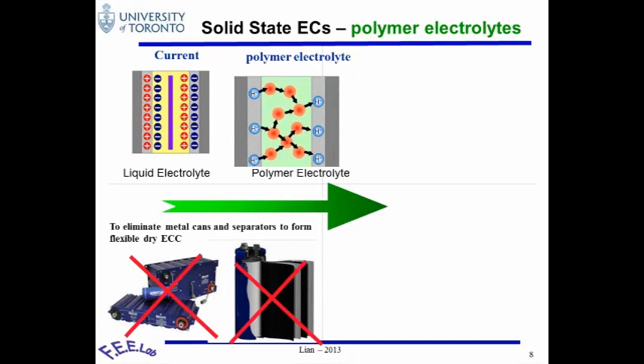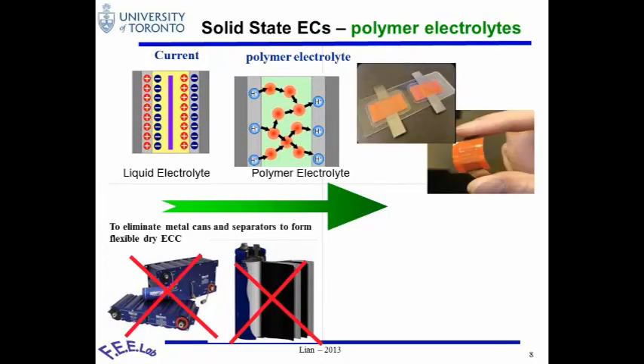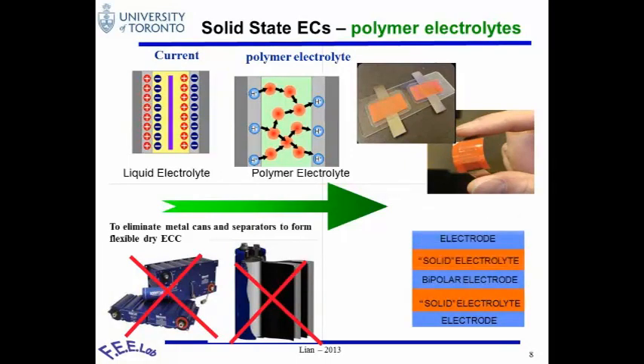And so with the polymer electrolyte, it can act as a glue, but meanwhile with ionic conducting, so that we can have not only a flexible device, but more importantly, we can really avoid having these dead weights in terms of packaging, so the energy density can be increased.